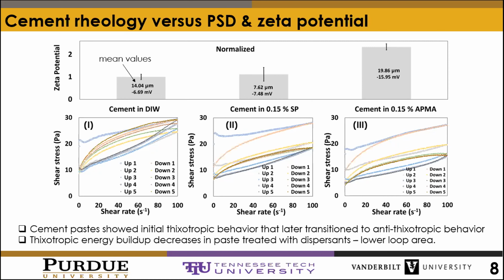Secondly, while ammonium polymethacrylate clearly changes the surface charge in a direction that should favor deflocculation, in fact, it doesn't. And the apparent particle size increases by more than double. Nonetheless, the rheology suggests that in fact, ammonium polymethacrylate has a lubricating effect, apparently. And once the paste begins to be sheared, it behaves as a flocculated material and transitions to anti-thixotropy.